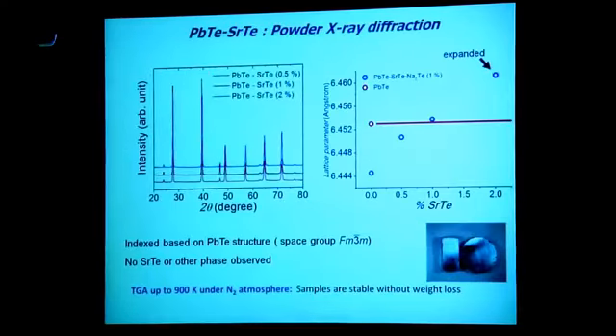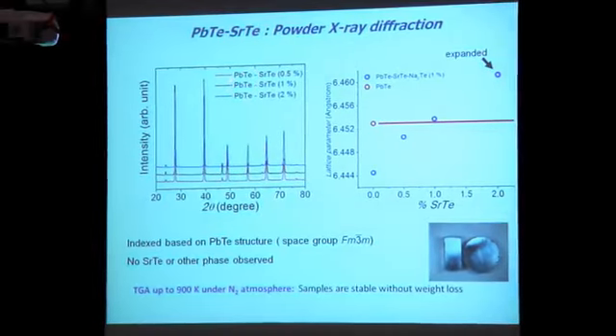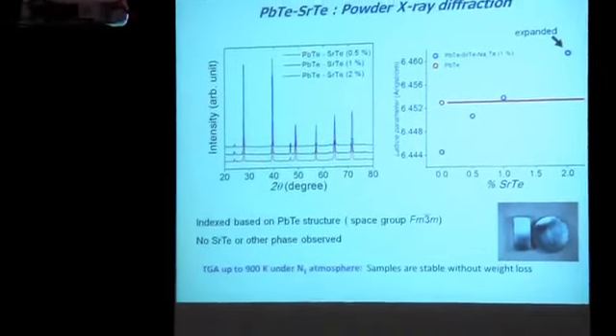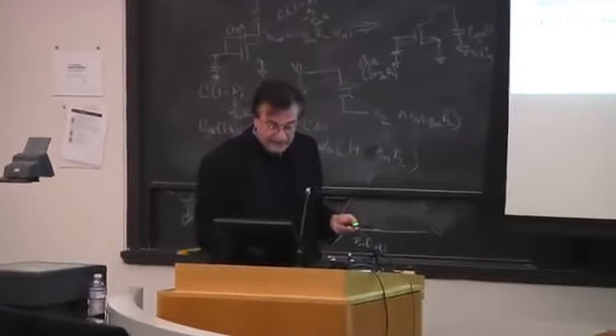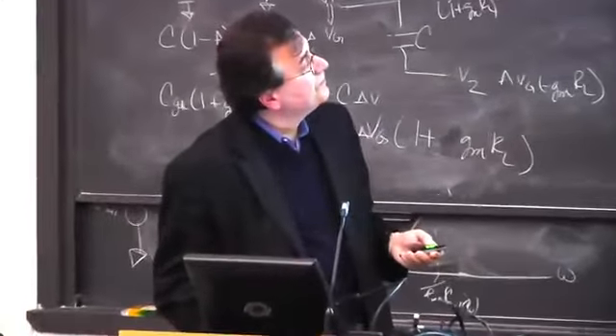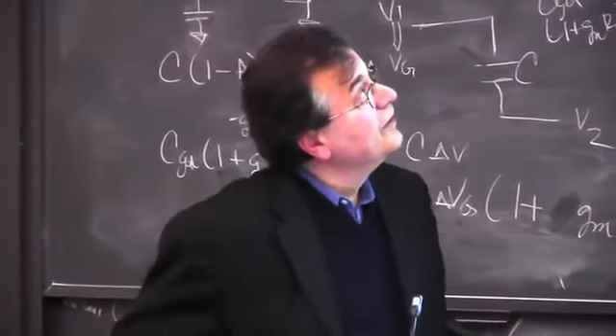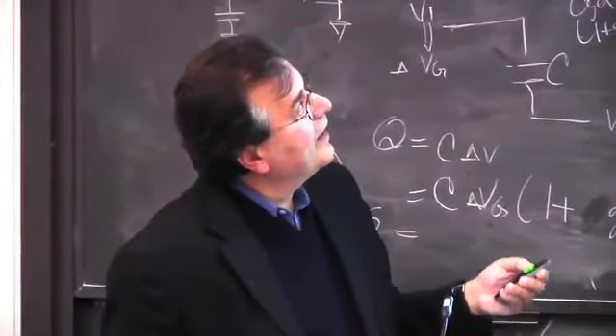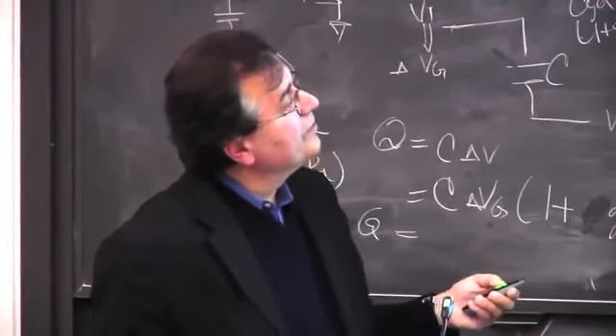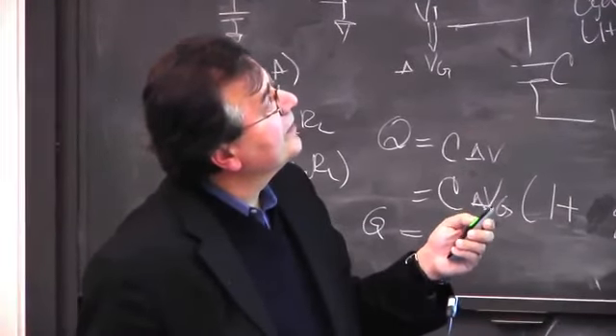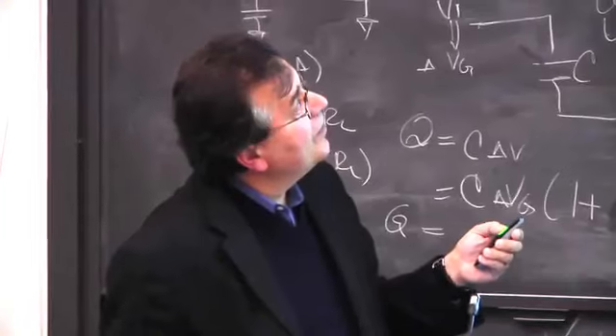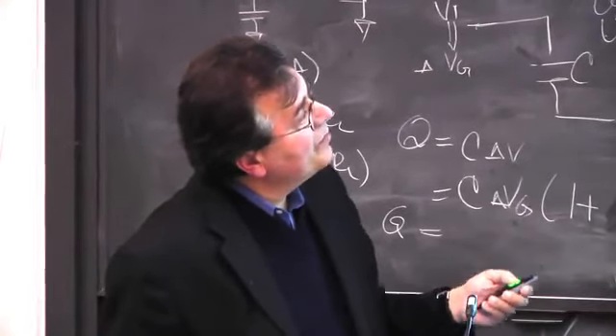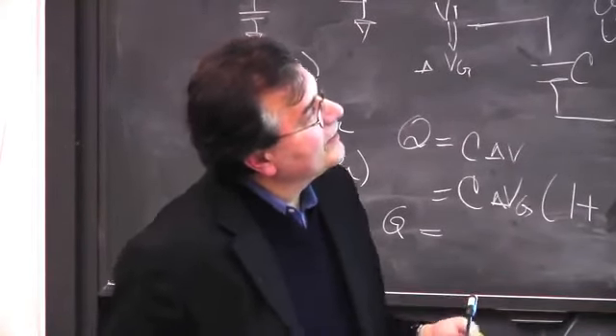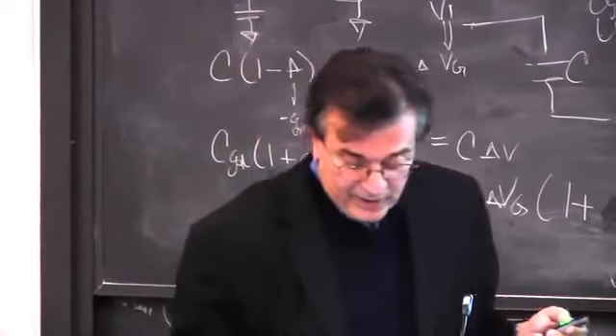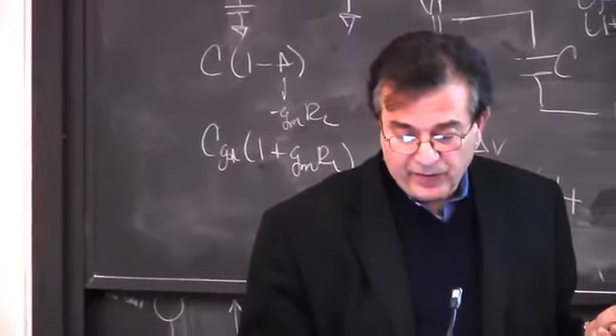So you can also add sodium. If you want to dope lead telluride p-type, you can add sodium. It has one electron less. It occupies a lead site, and it gives you holes. So if you add sodium, then you can make highly conductive samples. So this is room temperature. You get over 2,500 Siemens per centimeter. These all have the same sodium amount, so they have the same number of carriers, and they have a similar conductivity. So that's good behavior for hole doping.